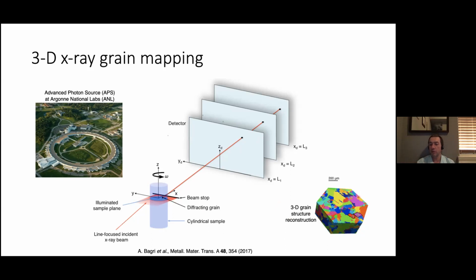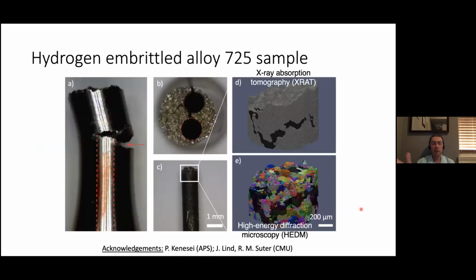And here's an example of one of those 3D reconstructions. Each one of the individual sort of patches of different color that you see here is a distinct grain. So you get both the shape of the grain, its location, as well as its crystallographic orientation. So this is a very powerful technique. We use this technique to study the sample that I showed you before. So here's that tensile specimen. We cut out millimeter diameter samples out of that specimen. This is just a sort of top view of where we cut those out. This is the 3D grain reconstruction that I'm showing you on the bottom. The technique, as it's called at APS, is high energy diffraction microscopy, or HEDM.